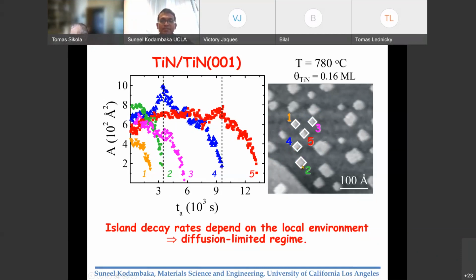So, which indicates that, mainly because there is mass conservation, and part of the reason is because as island 2 is decreasing in size, as it's losing atoms, some of the atoms are likely going to these larger step edges, but a few of the atoms are attaching to this other island 4. So even though island 4 is smaller to start with, it gains some atoms because island 2 starts to lose all its atoms because it's in the vicinity of a straight step edge. The concentration gradient is higher here. Okay. So this type of behavior is characteristic of surface diffusion limited processes. So if diffusion is the limiting step, then you would observe this type of local environment dependent change in the growth or decay kinetics. So now we know that surface diffusion is the limiting behavior.